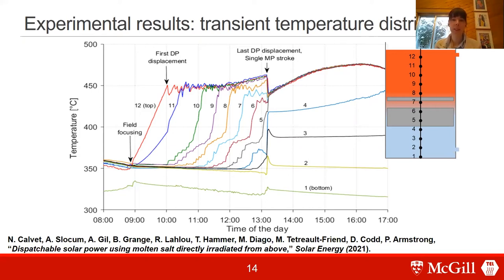So here you can see the temperature profile in the molten salt for a charge between 350 and 475 degrees Celsius. So the objective of this experiment was to gradually heat the hot salt layer at a uniform temperature. So you can see each curve corresponds to a temperature probe somewhere in the tank, and throughout the day, the divider plate would move, so we keep the constant temperature on the top.